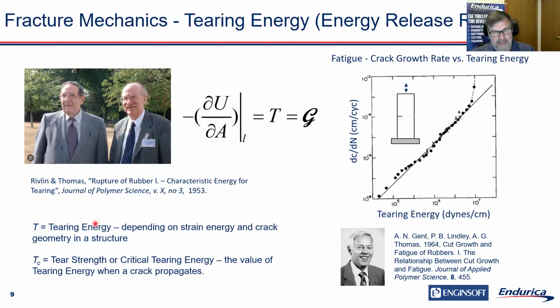The value of this tearing energy is like the level of stress or strain in your product, and it changes throughout the product due to the geometry and the loading, and they all have some level. When that level reaches a critical value, say the tear strength or the critical tearing energy, that now is a material property. It's like the ultimate strength or the yield strength for metals. It's the level of tearing energy at which a crack will start to grow. So that's an important quantity to know for your material.